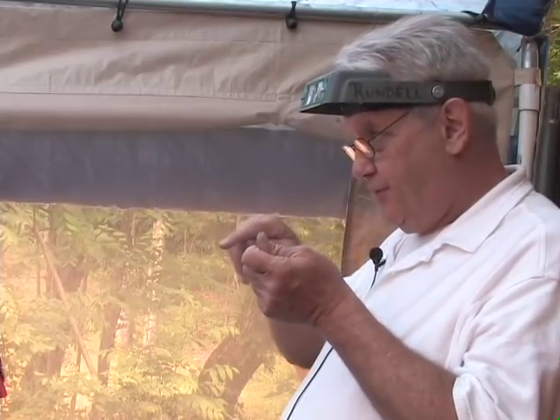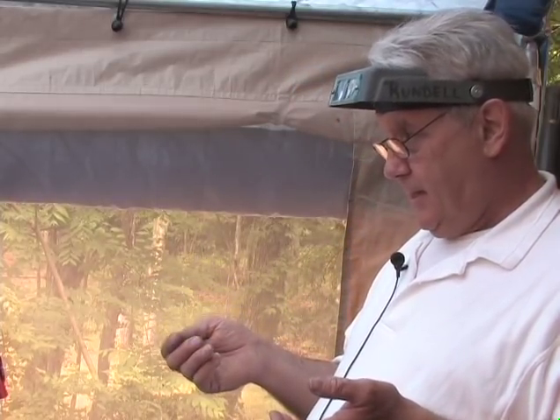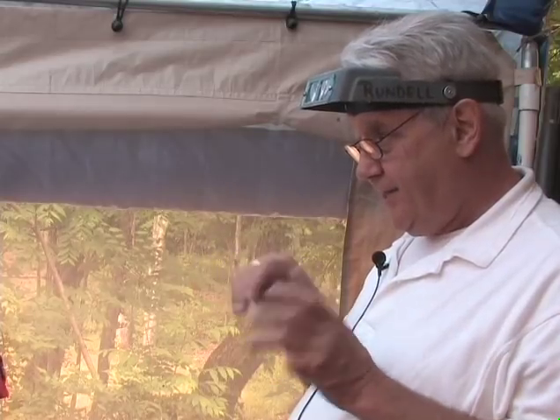When you go over that and start to punch it in, all at once your design starts to come up through the sheet gold. So now you can see where the perimeter of your gold is, and you can take a knife and remove all the excess, then come back and do the final punch work and also the final burnishing. Then I go over that, usually with about a 600 grit wet or dry paper, so that I've got a surface that I can draw on, so I can detail it.